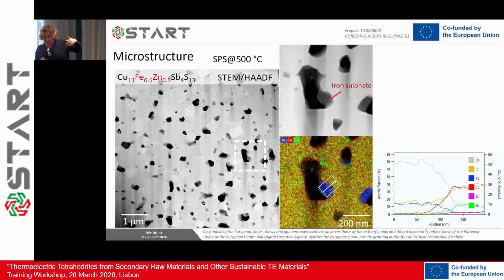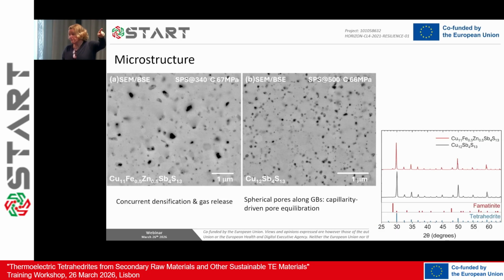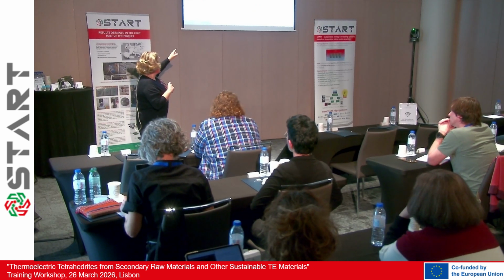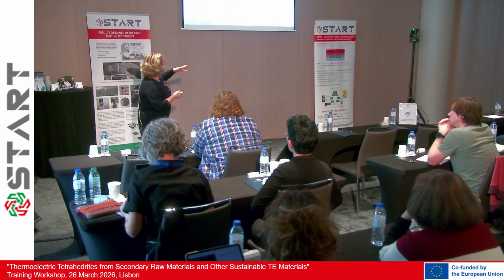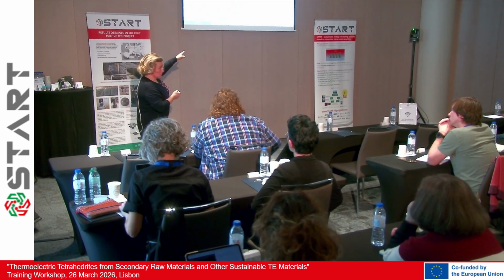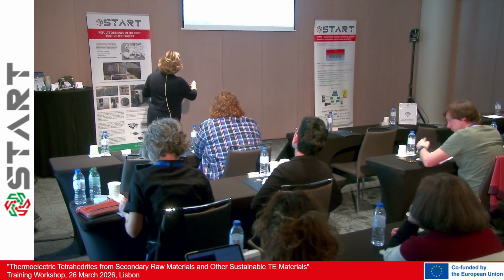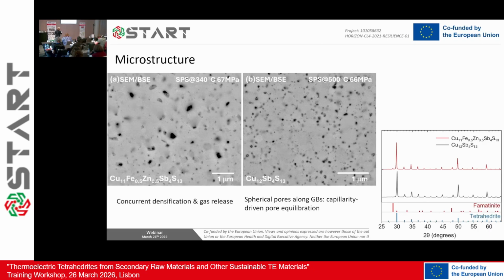So these very fine pores resulted from the process. Initially we started to make SPS consolidations with just one disk in the matrix. Then in the industrial upscale, we started to make it with more disks. When we made it with more disks, the porosity became much finer. We don't really know why, but this one here, which corresponds to the same type of material, was made with one disk. These two were also made with one disk.